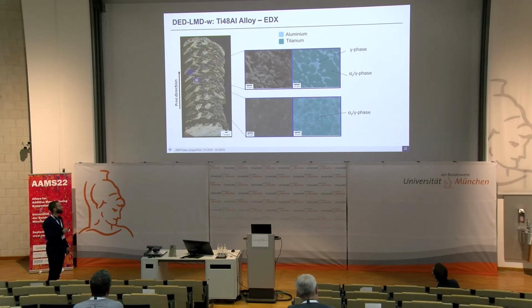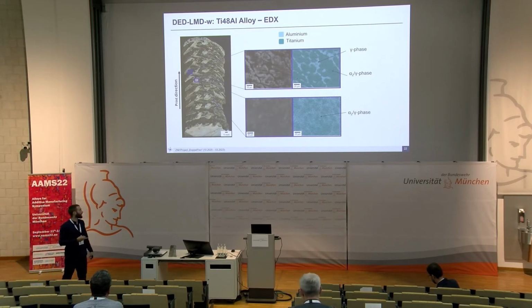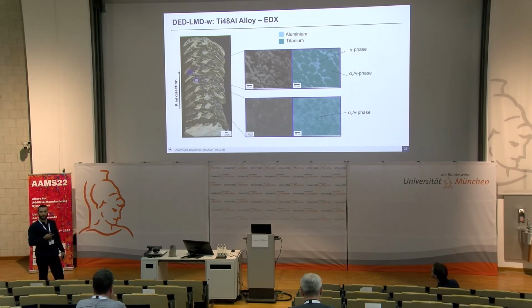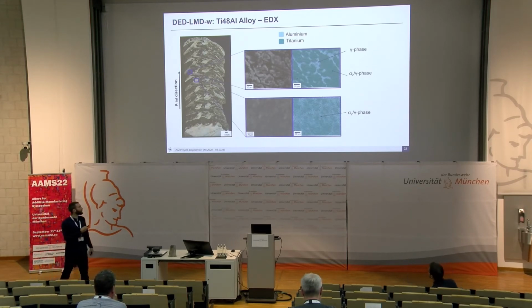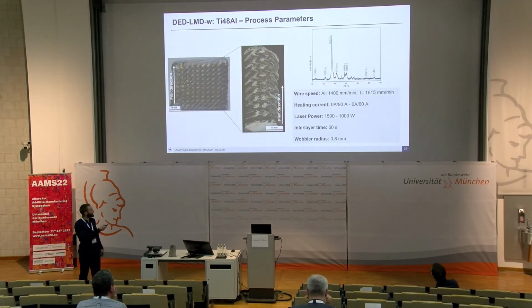When we have a closer look, we have mainly two structures. One is a dendritic one, and one is a lamellar one. If we look at these EDX mappings, we can see that we have some parts with a high aluminium content and some parts with a less high aluminium content. This refers to the gamma phase and the alpha 2 gamma phase, which is also proven by our XRD samples on the slide before, as you can see here.